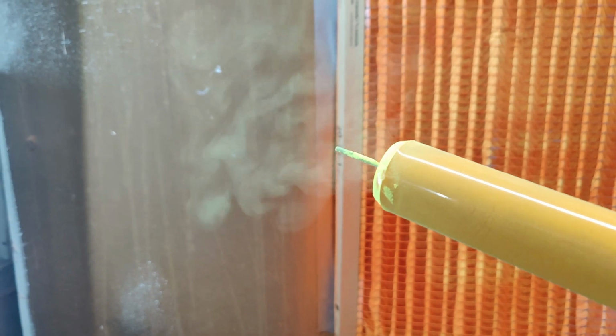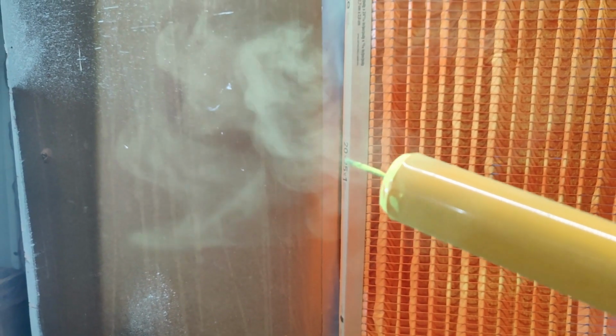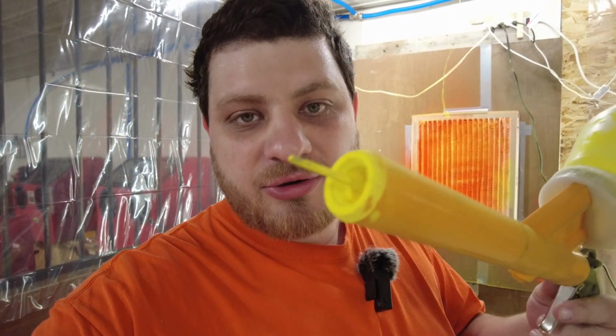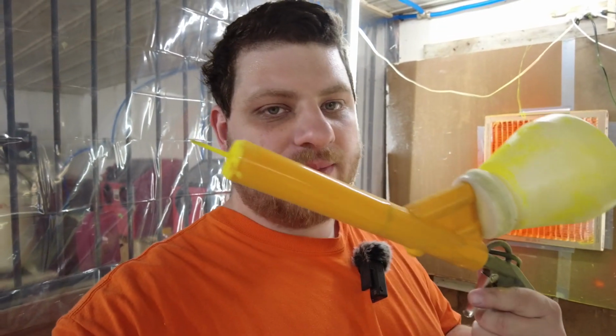The powder coat gets poofed out of the end of this gun. It's not really a spray, they call it a cloud, kind of like vaping. On its own, that powder doesn't actually want to stick to anything. So that little stick coming out of the end of the gun is an electrode that gives a positive charge to the particles coming out of the end of the gun. This little clip goes on the part that you're coating, giving it a negative charge. As you're spraying, you have positively charged particles mingling around with your negatively charged parts, and inevitably they're gonna merge.